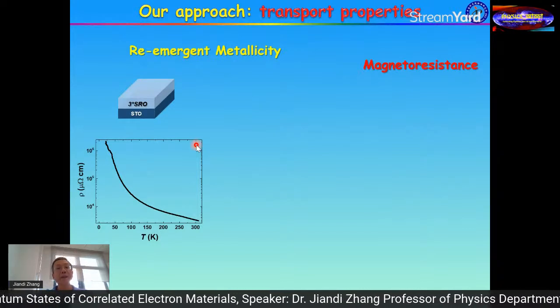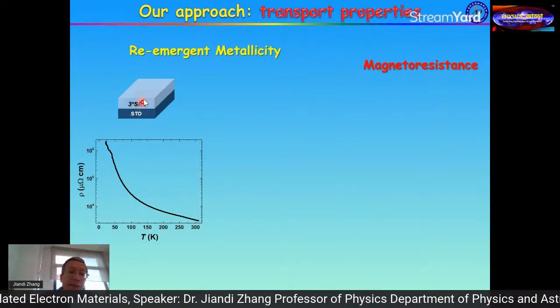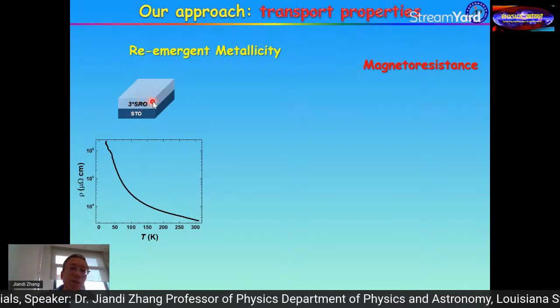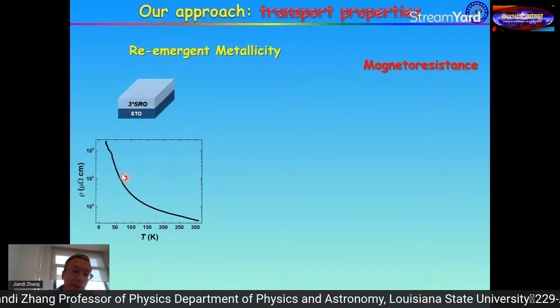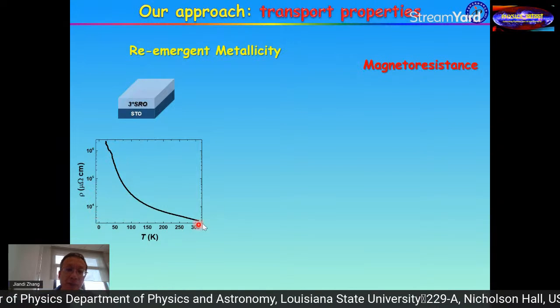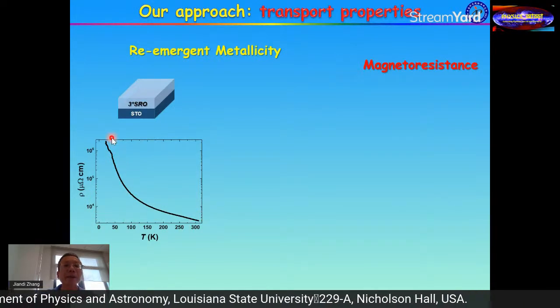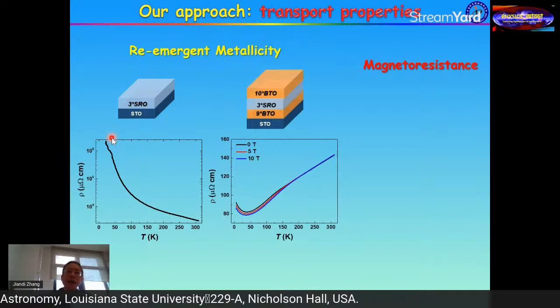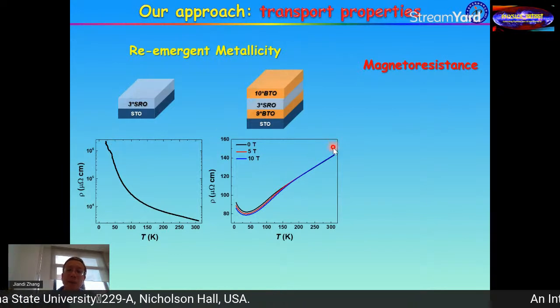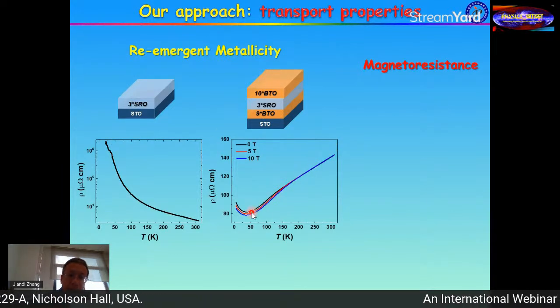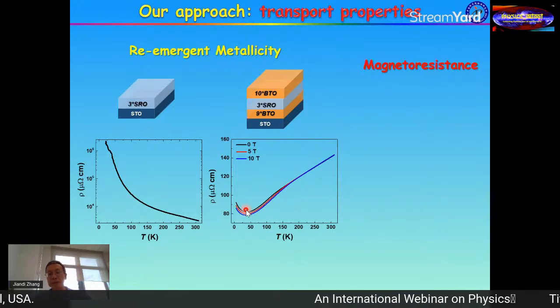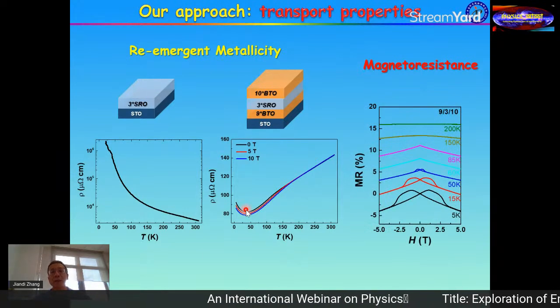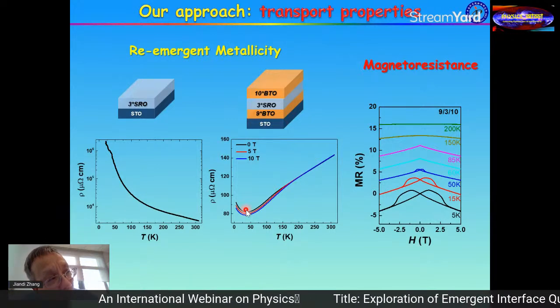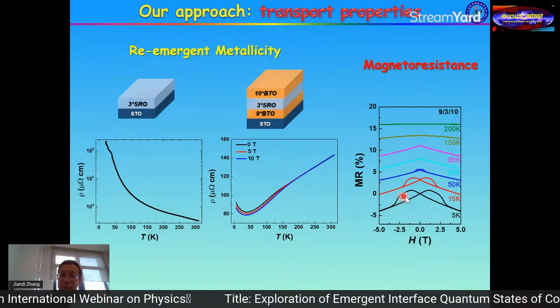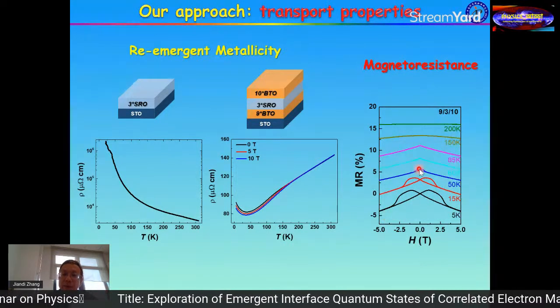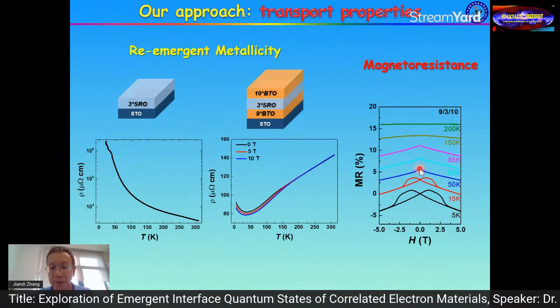All right. So once we look at that, the magnetic property really can be enhanced, and look at whether it is a metal or not. So if I only grow, again, just 3 layers of the strontium ruthenate, it is an insulator. Okay, this is resistivity as a function of temperature. It is an insulator. While if I put, again, this sandwich, it turns into metallic behavior. So again, it's showing you exactly what's going on. And you can also look at the magnetoresistance. The characteristic butterfly behavior tells you it is ferromagnetic in the ground state.